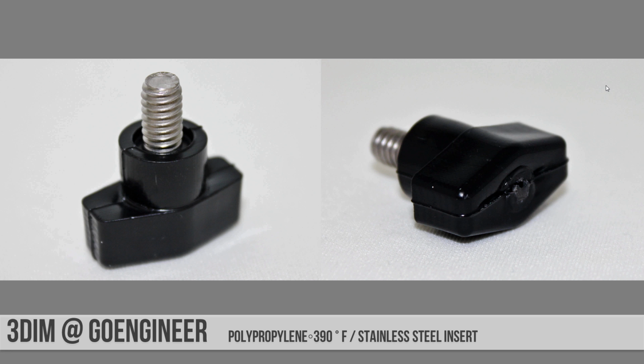These were polypropylene. I injected at 390 degrees Fahrenheit, so a little bit higher than recommended. The reason for that is my molds were cold and I needed good flow around the hex head. Stainless steel insert. So we got a little bit of flashing on that, but overall, that's a great looking part. And it performs just as well as the part that I mimic in terms of twisting it as hard as you can and it doesn't break.